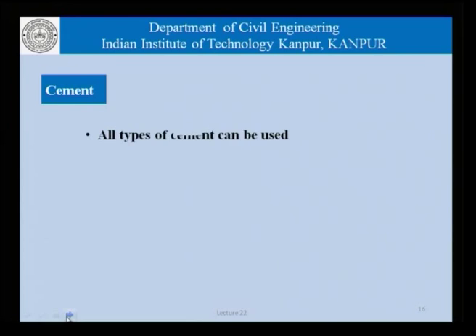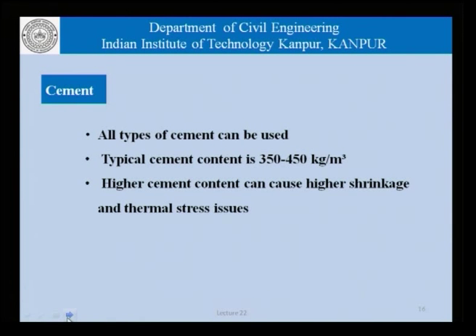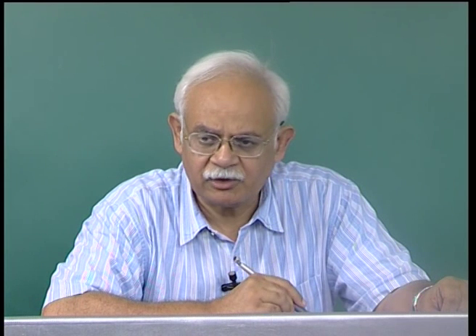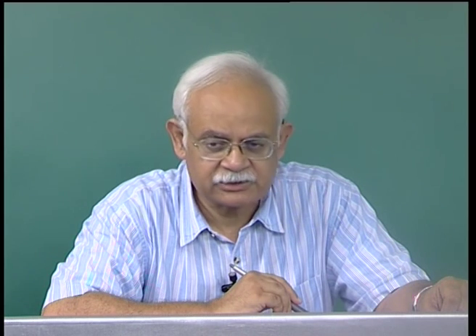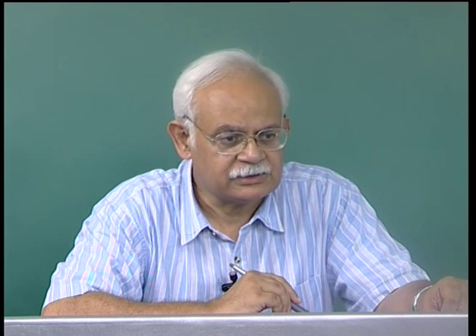As far as cement is concerned, we can obviously use almost any type of cement. The typical cement content is no different from normal concrete. It's about 350 to 450 kgs a cubic meter. And higher cement content, obviously, would end up with higher shrinkage and thermal stress issues. And therefore, even though we require a higher paste volume or a higher powder volume in the paste, it's not always advisable to use cement.